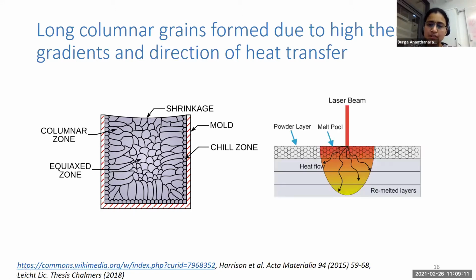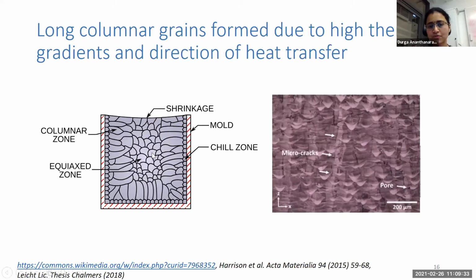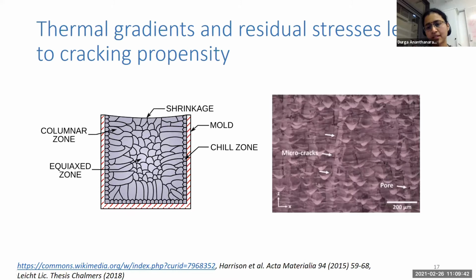But in the case of SLM, we have the laser beam melting maybe the first layer and some layers below. And you have a melt pool that forms. And then due to the direction of the thermal gradients and heat transfer, you have grains growing along that. And the growth rate is so fast that you probably don't even have time for this transition to happen. And we end up with these long columnar grains. And due to this type of grain structure and the stresses, we have a lot of cracks forming as well. So that's about the grain structure and the cracking.